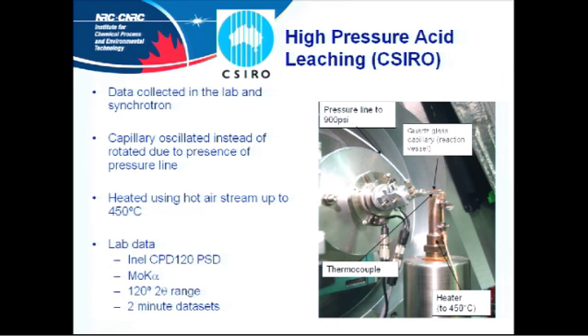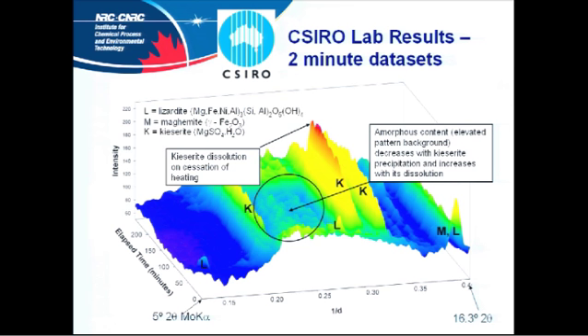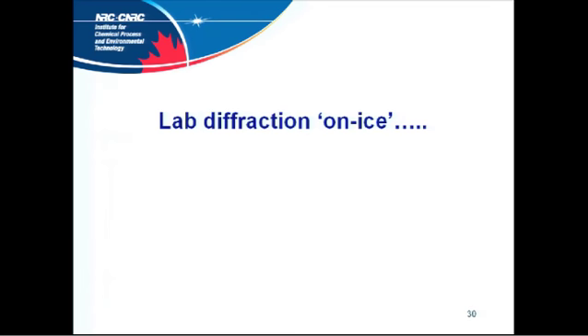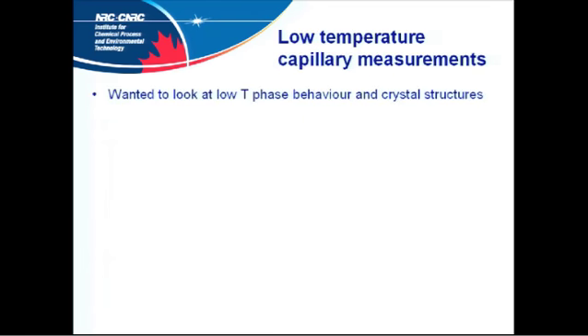They use the lab system for some of their work, so an INEL, Moly. They've obviously got a large range PSD. And this is effectively the kind of data they get. And you see here that in kieserite dissolution, it starts to drop off when you actually finish the heating, and the amorphous background decreases and then increases with the dissolution. So you get some of the information you want.